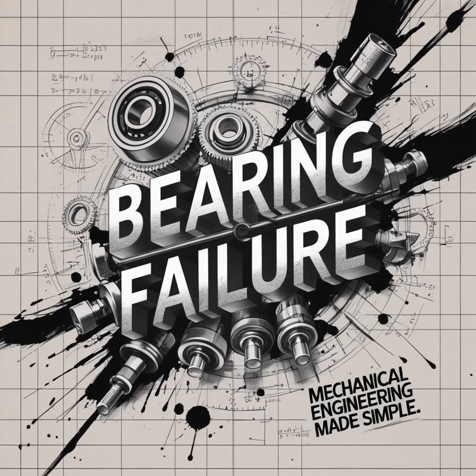And what about liquid contaminants? Liquids, water, acids, process fluids, they're the chemical enemies. They attack the lubricant itself, stripping its effectiveness and just tanking its viscosity. If water gets in, it can cause corrosive etching. And that kind of damage often appears when the machine is idle, right? Yes, the static etching phenomenon. It's a great example of a failure that happens when the equipment is turned off.